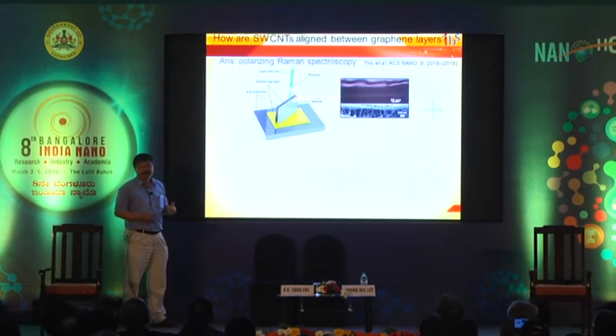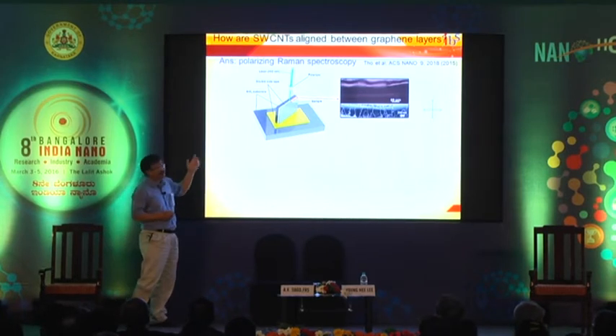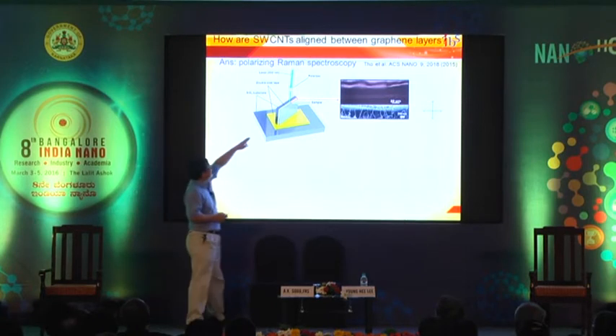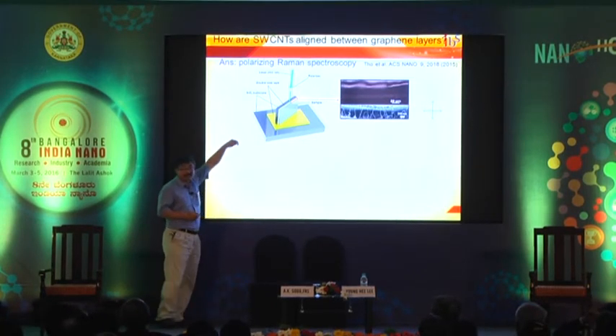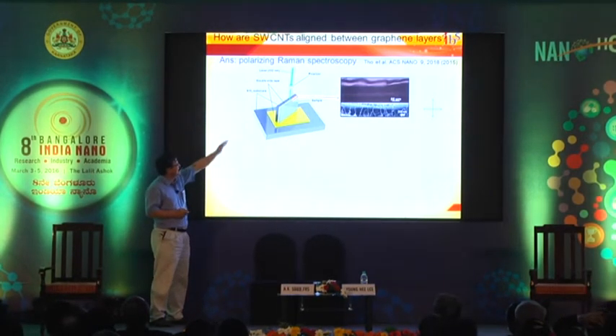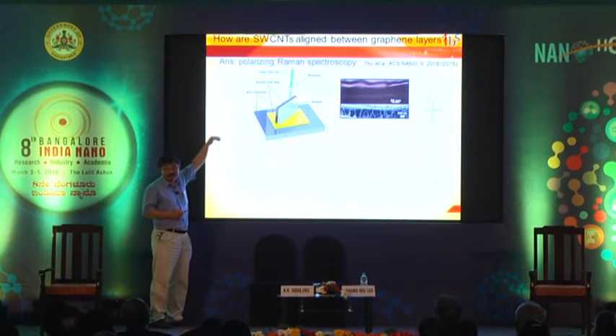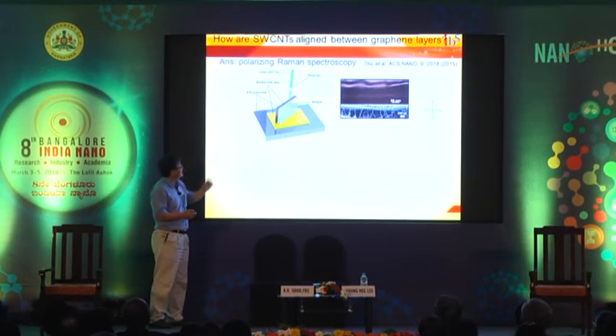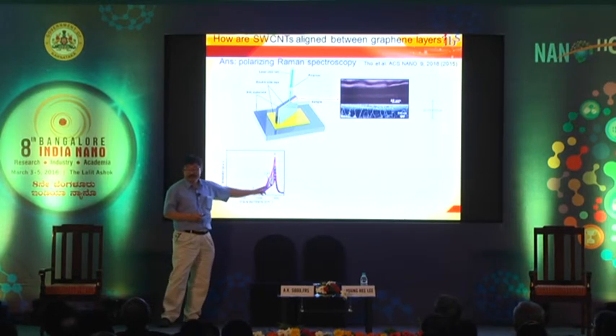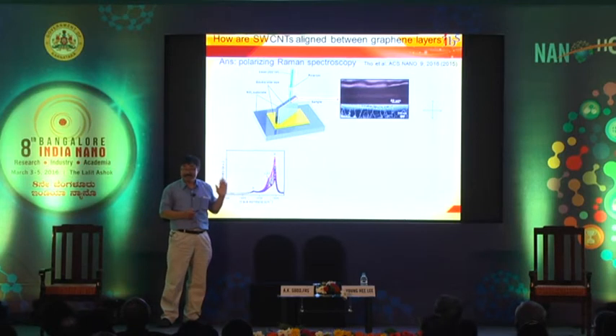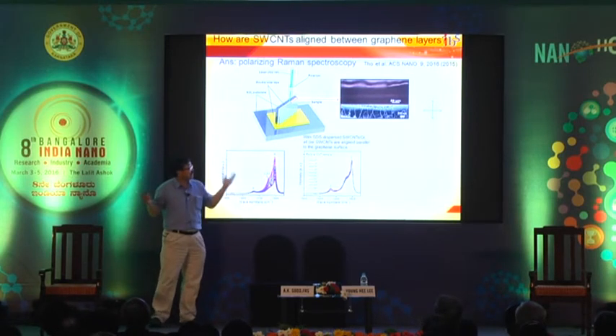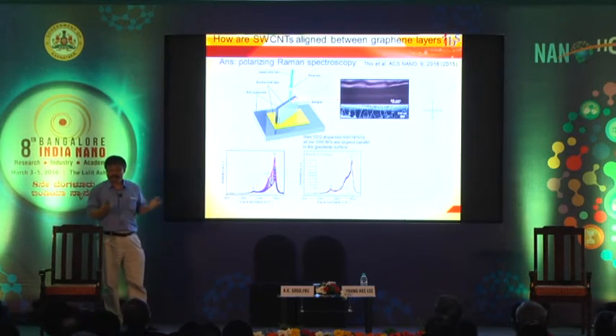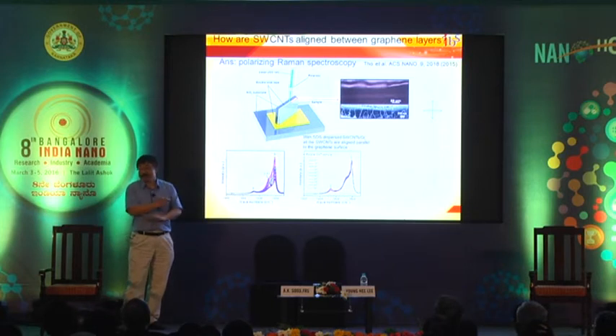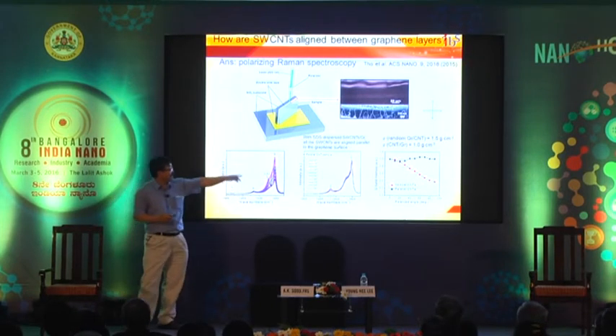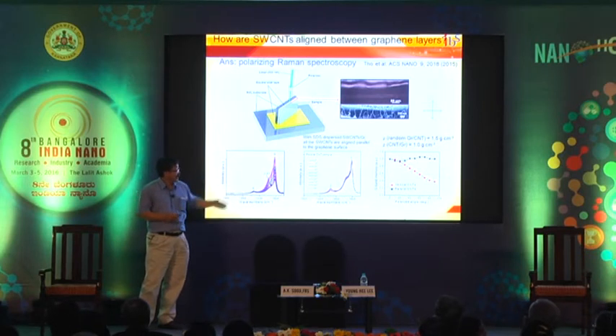And how do we prove this alignment of nanotubes? In this case, we simply use polarized Raman. You shine the light with a polarizer, and when the light is parallel to the nanotube, it penetrates, and when you rotate this polarizer, you can see the intensity of the G-band changes. That means the nanotubes are really aligned perpendicular. But if you use just a regular surfactant like SDS, which is negatively charged, you don't see that effect at all. The nanotubes are completely randomly aligned. So you see big changes in the G-band intensity as you change the polarizing angle. So this is evidence of the nanotube alignment.